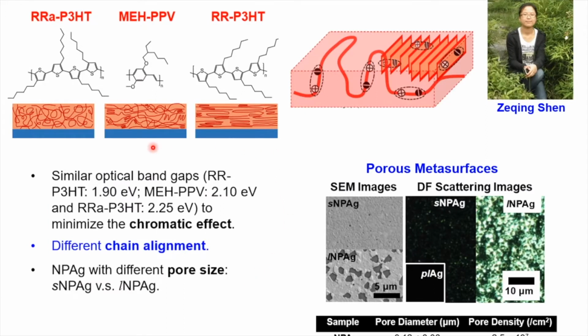In this particular study, we were interested in understanding the role of the semiconducting polymer morphology on the fluorescence enhancement. So we studied 3 different polymers, each with very similar wavelength emission, but different actual film morphologies. So typically, regiorandom P3HT has a very amorphous polymer chain orientation in the film. It's been spin coated into a film. MEHPPV is more ordered, but also has some amorphous regions.